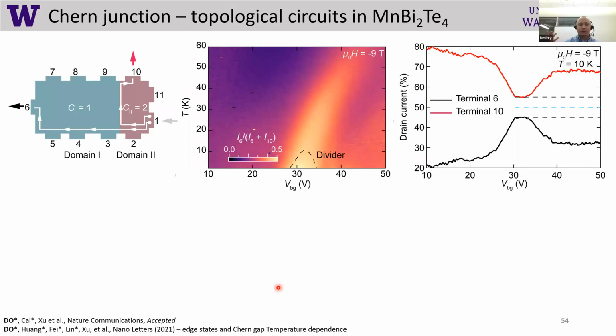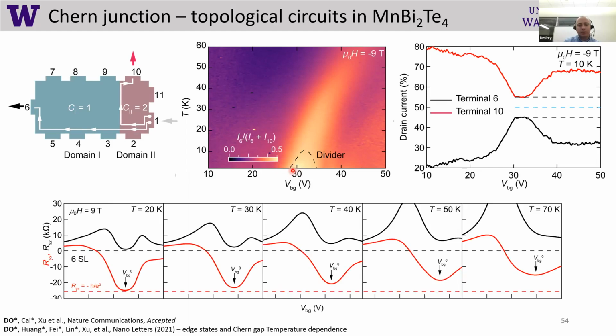Finally, the important aspect of all these topological circuits would be the temperature. So we tested to see how high we can go with temperature to still observe the topological effects. We did previous studies on temperature dependencies. They are shown here. This is actually a lower quality sample than the one I'm showing on top. So this is what I call generation 1. In this case, we could see that up to 70 Kelvin, we can still observe sizable RXY, meaning that topological effects are still there.